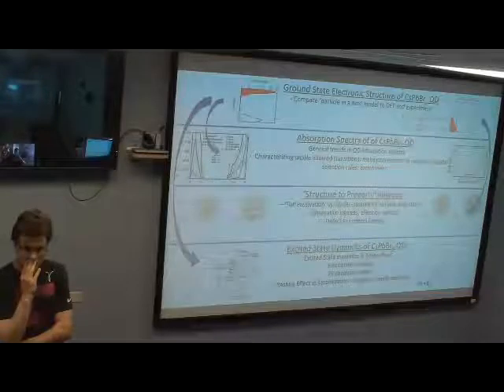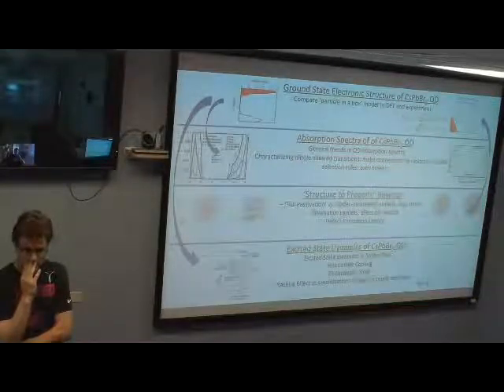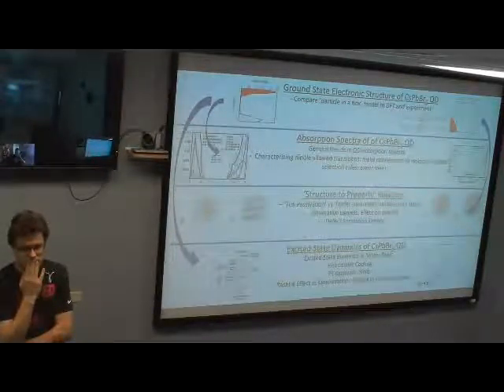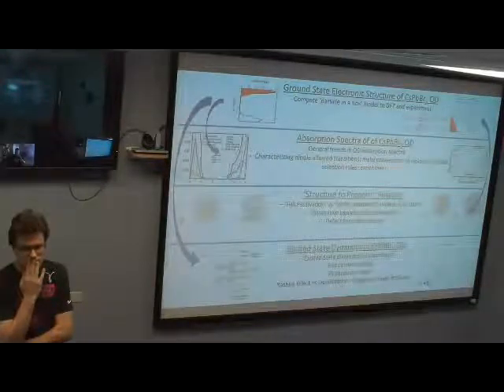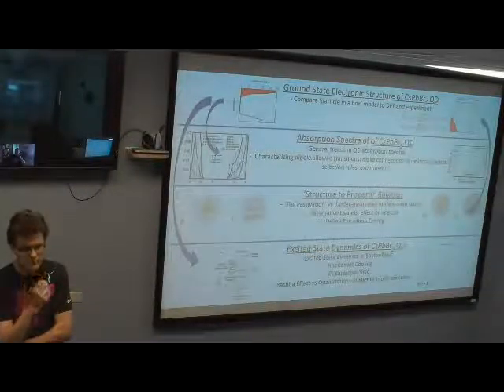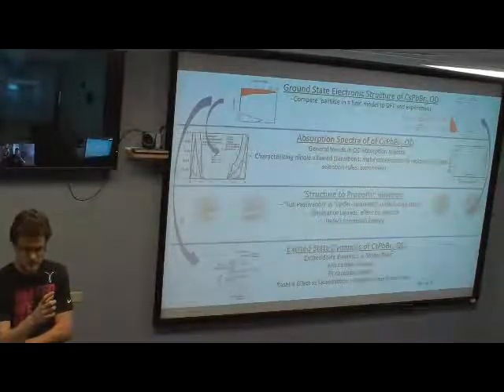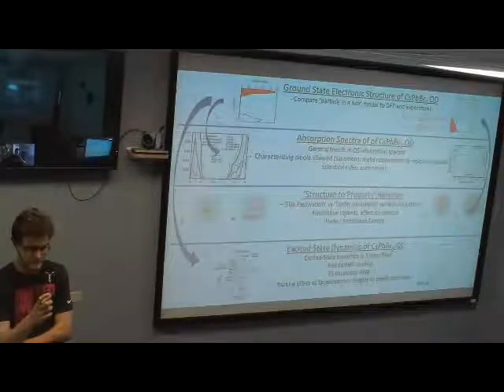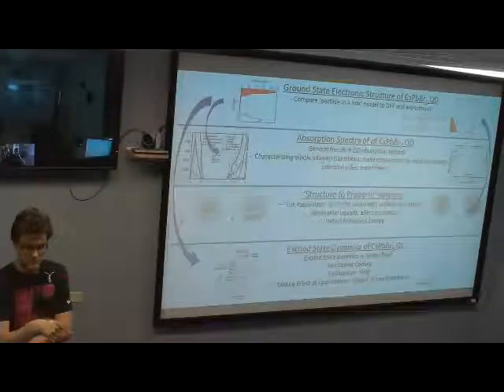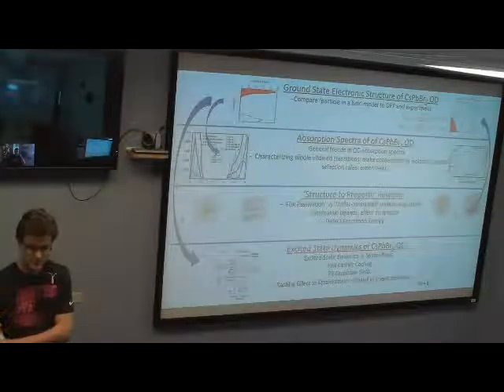But we're talking about intraband relaxation, what you call hot carrier cooling. What you're saying is right, but how does this really deal with your relaxation? Okay, what happens with electronic levels when you go to confined systems? They become more sparse and further apart, and more discrete. So you have more bands, or higher energy. How does this affect the interaction with resonant vibrations? We need more of them, or the probability of a phonon with a certain energy to jump the gap is less, so it takes longer. So it should be slow, actually, right?